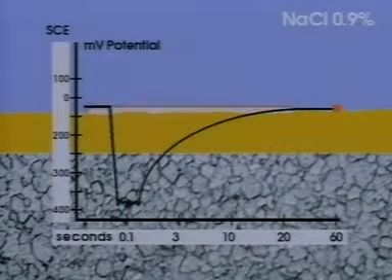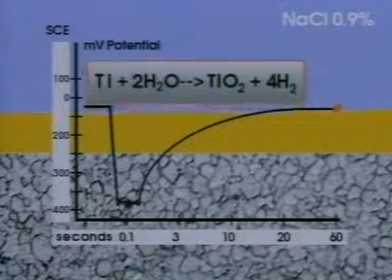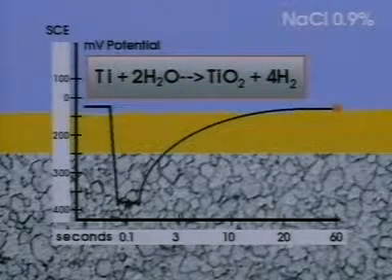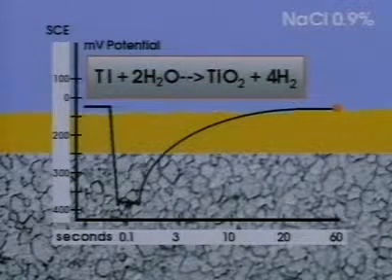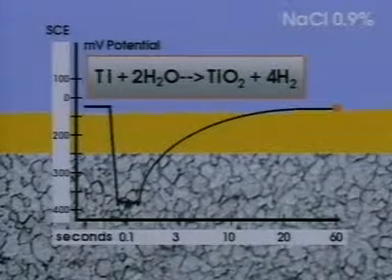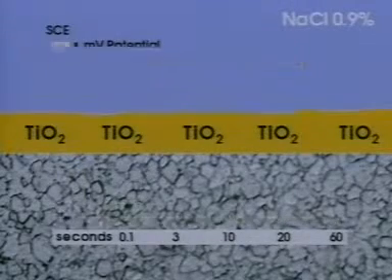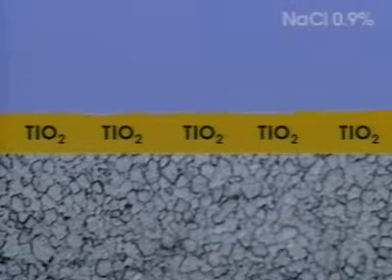At body temperature with a chloride concentration around an implant, the production of oxide from water is so efficient that corrosion can never produce enough ions to trigger a pitting situation. A defect in the passive film on titanium will always repassivate.